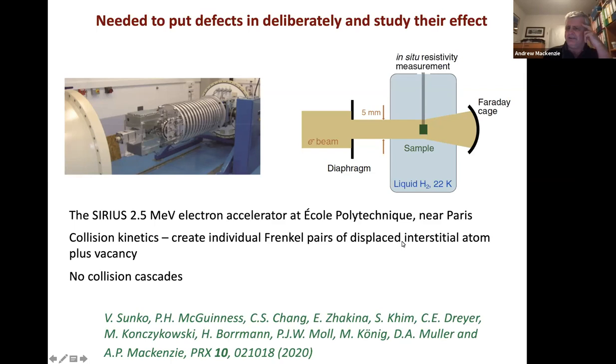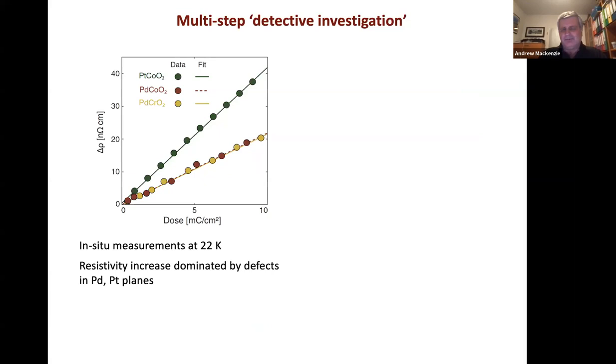which will be a vacancy plus a displaced interstitial atom. And they're beautifully set up to do this because they also allow you to do it at low temperatures, because you don't want to anneal the atom back into its original site again. So you stay down at low temperatures in liquid hydrogen for heat capacity reasons rather than liquid helium. And then they also allow you to do an in situ measurement of the resistivity as you're doing the bombardment process. So it's an ideal instrument with which to try this, but I'm trivializing the experiment. This was an extremely difficult experiment, and the dedication that the guys showed through multiple visits to really get it to work and the skill they showed was extremely impressive to me.